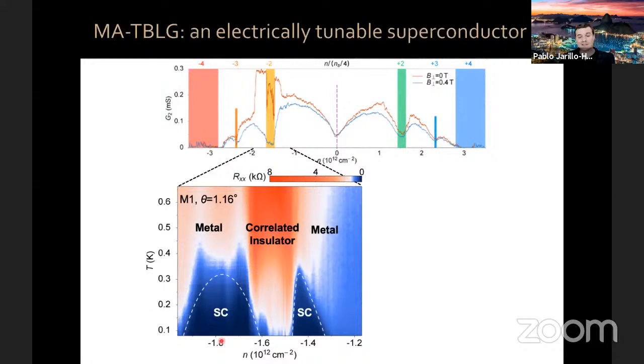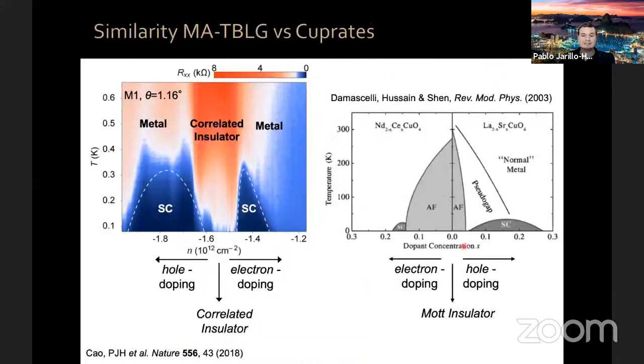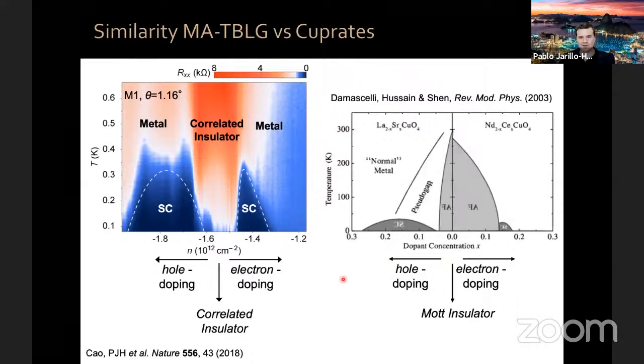When I saw this behavior, this resistivity versus temperature and doping, I was really shocked. This reminded me immediately of the hundreds and hundreds of times that I have seen pictures like this. This is the phase diagram of the high temperature cuprate superconductor family. Here in the cuprates, they put hole doping in this direction, electron doping in this direction, so let me flip this so that it's in the right direction. Now, in the cuprates, zero doping means actually 1 electron per copper site. This is a Mott insulator. You add holes, you have a superconducting dome. You add electrons, you have another superconducting dome.